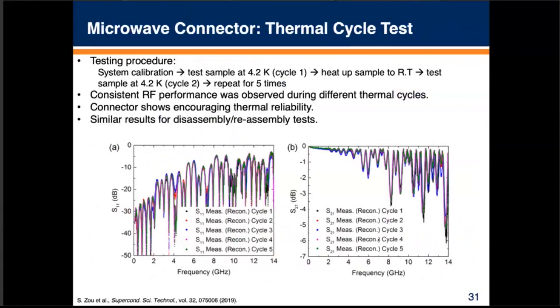Some other important aspects of this are thermal cycle reliability. If you're going to use these over and over again, how do they behave when you thermal cycle them? Even though it has this complex structure, which I hope makes sense now that I've described it, you can see that after we cycled this five times, going from 4K up to room temperature and back down, we get quite good thermal cycle reliability. I didn't include the results because they look very similar, but if we take it apart and reassemble it, we see about the same amount of variation from disassembly and reassembly. All of these were quite promising for this bridging connector approach.